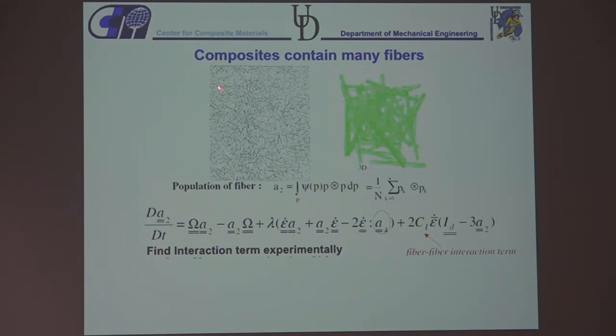So basically, instead of describing the orientation of one fiber, we describe the orientation state with the second order orientation tensor. So the tensor gives you the orientation state. And it's also very nice because if you want to find mechanical properties, your elastic modulus can be a fourth order tensor, so you can actually use the orientation state to get those values. And so this allowed us to actually predict the orientation state from flow.